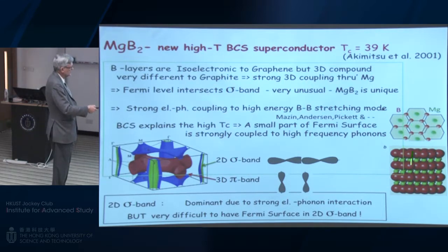So there is a much stronger three-dimensional coupling, and this means that, unlike the graphite and graphene carbon ones where the Fermi energy lies always in this pi band, that's the p orbitals which are perpendicular to these planes, it actually causes so much three-dimensionality that a little sliver of this sigma band, which is normally totally occupied, certainly not involving the Fermi energy in graphite or graphene, is now at the Fermi energy. And so what does that do? Well, first of all, it gives you a very strong electron-phonon coupling because these sigma band orbitals, p orbitals, are the ones in the plane. They point towards each other. So if you have a vibration which changes this distance, it strongly couples to the sigma band.